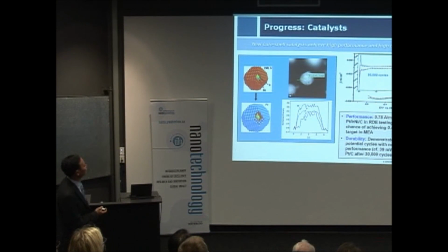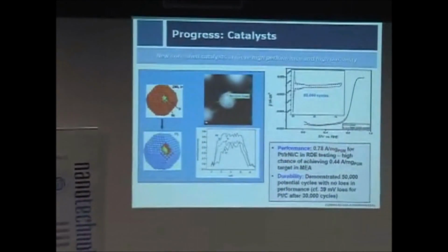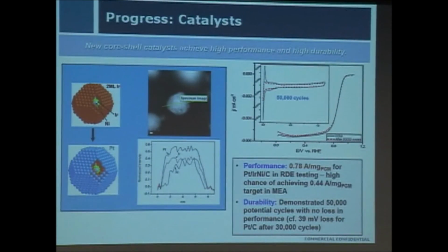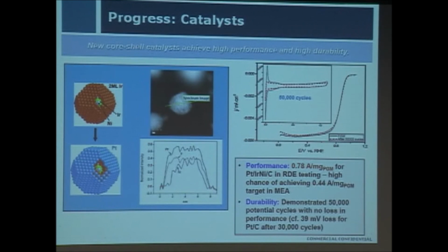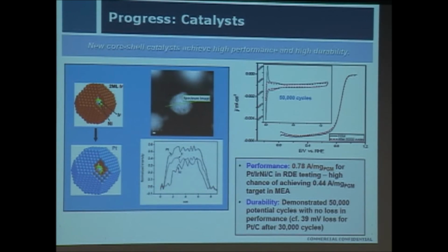Another example is this core-shell catalyst. I particularly chose those because they are mostly related to nanostructured catalysts. They also have an opportunity to continue reducing platinum usage because they have a 4 times improvement in mass activity, and they also demonstrate extremely good durability. For example, with 50,000 potential cycles, which mimics the start-stop of a car in the real world, there's almost no performance loss. However, if you use the existing carbon-supported platinum catalyst, even after 30,000 cycles, it is already close to 40 millivolts of performance loss.